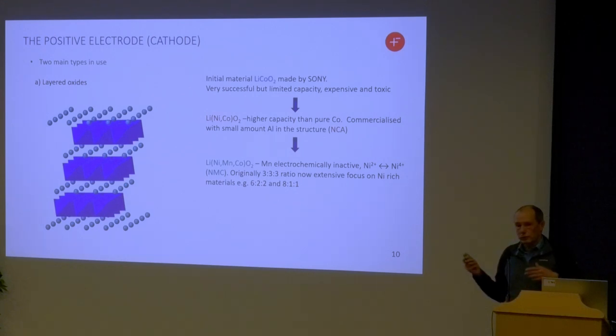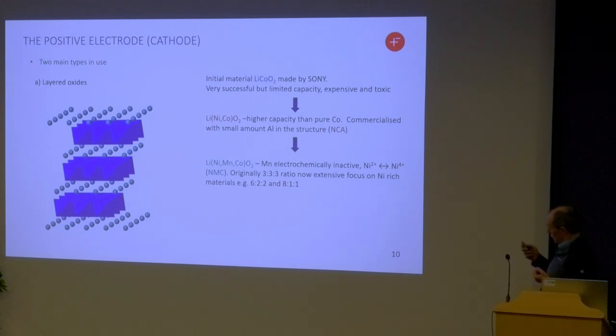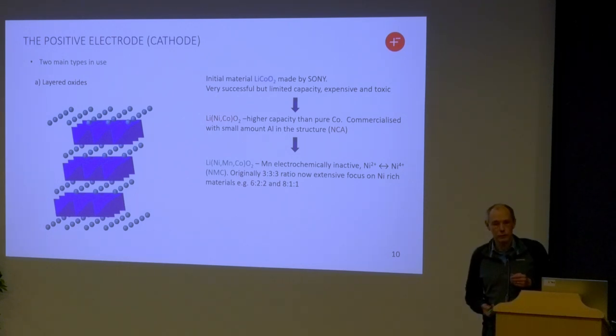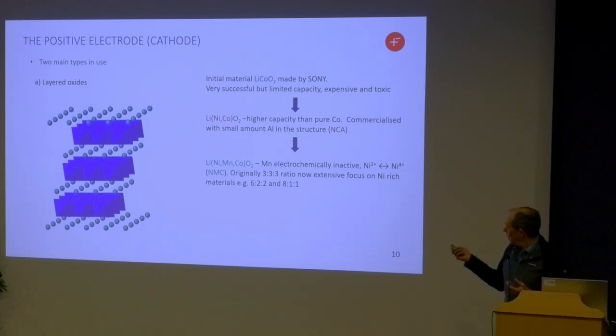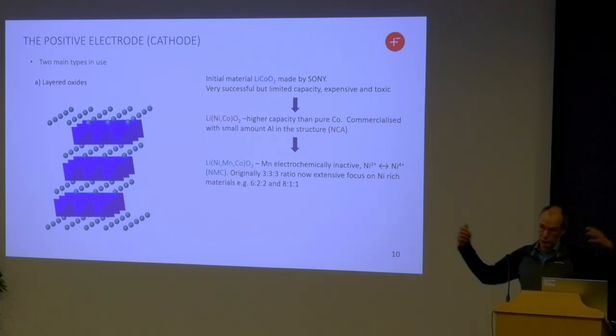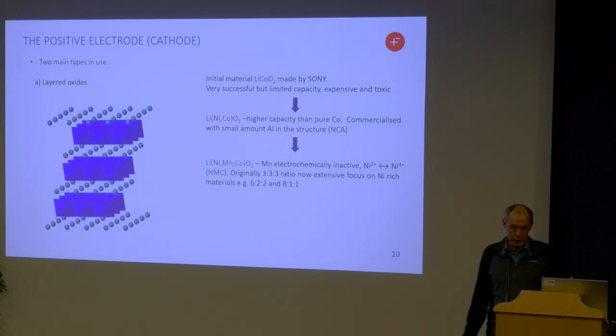Then people moved on to replacing cobalt by nickel. It would be nice if you could replace all the cobalt by nickel, but nickel likes to be nickel 2 plus, and nickel 2 plus is about the same size as lithium. So what happens is you get some nickel 2 plus going where the lithium should be, and that obviously makes it harder to get the lithium in and out. So nickel on its own, not so successful, but if you mix nickel and cobalt, then you can get a material that works very well. It's commercialized, and this normally has a small amount of aluminium, about 5%, which in terms of the battery capacity is doing nothing, but it does stabilize the structure. And it's typically called NCA.